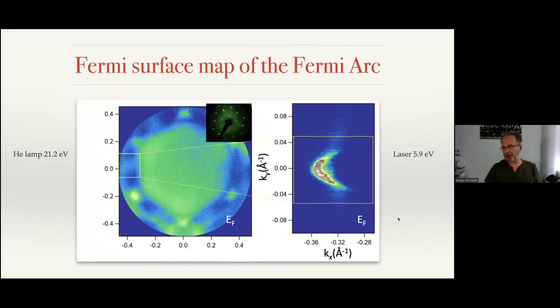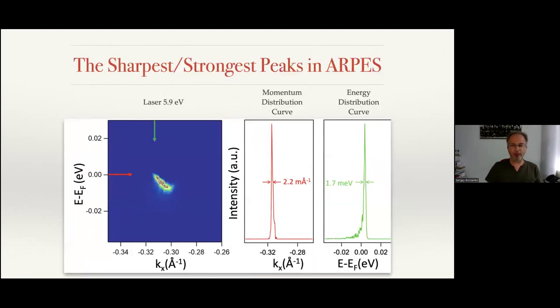And then if you know a lot about how to measure the Fermi arcs, you can get this kind of image. This is a very big breakthrough in comparison even with our previous measurements. So these are very new data, and you see how nicely we can resolve the Fermi arcs. Then, as I said, at that time we thought that was a record. So now I can tell you, this is the record.